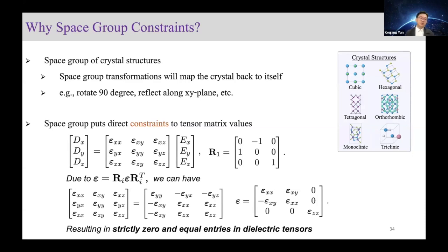Here I show an example of a rotation of 90 degrees for the dielectric tensors. For example, the rotation matrix by 90 degrees can be represented as this. And due to the equivariance I mentioned before, if the structure has this kind of symmetry, then the left-hand side will equal the right-hand side for this R1. And by using this equation, we can directly get that the xz entry will equal minus yz, where yz will equal xz, and in the end, xz will equal minus xz. And with this being said, xz will equal 0. And similarly, there will be some equal entries like this one, and opposite entries like this one and this one. So in short, space group will result in strictly 0 and equal entries in dielectric tensors, and that's why it's important.